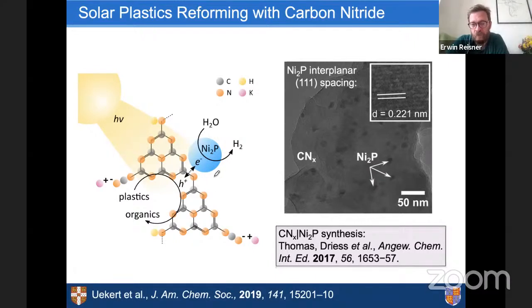And nickel phosphide is a known hydrogen evolution catalyst. And since this forms a nice solid-solid interface here, we actually have a much more robust photocatalytic system that you can easily separate and reuse. So recyclability of the photocatalytic system is important to us. And this here would be a very nice example where we can just centrifuge off our carbon nitride and reuse it many, many times for photoreforming in this case.